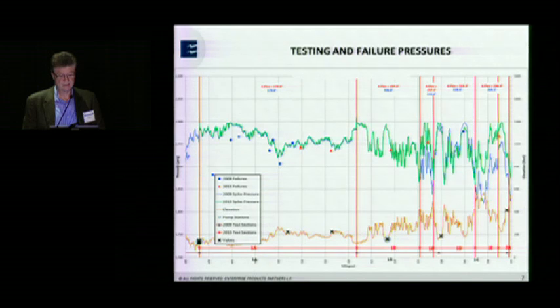And the blue dots represent failures that occurred in 2009. You can see that some of them are below the test pressure we performed, but that's not necessarily unusual because the previous hydrostatic test was lower than that. It was about, on average, 154 PSI lower. So what we're doing is failing seam defects that have been there since day one.